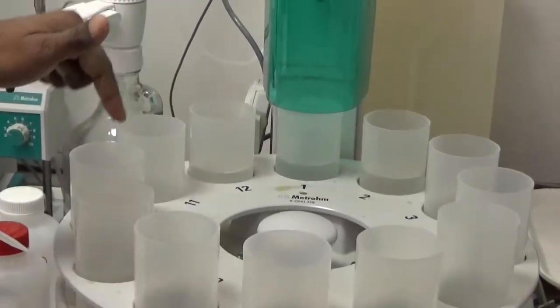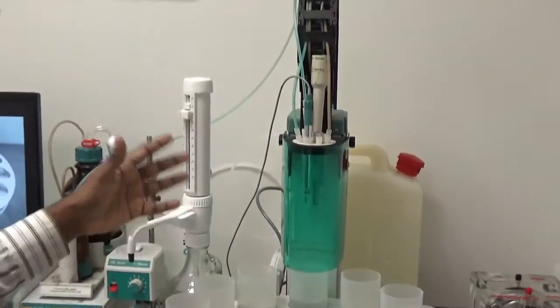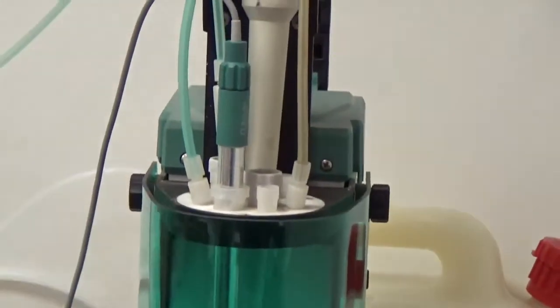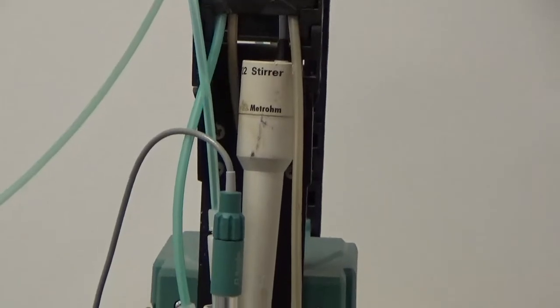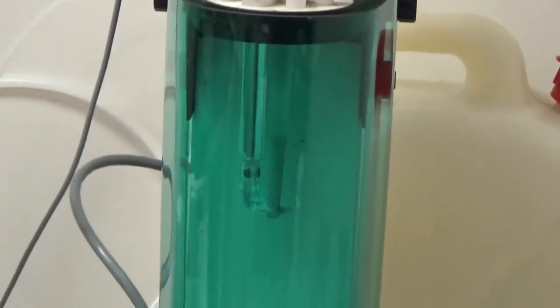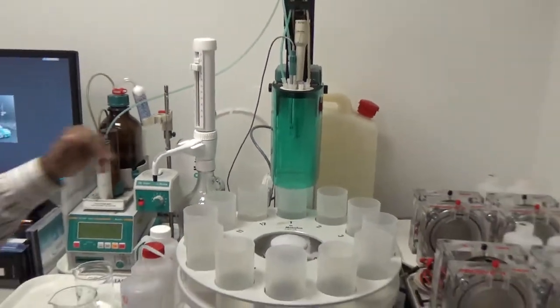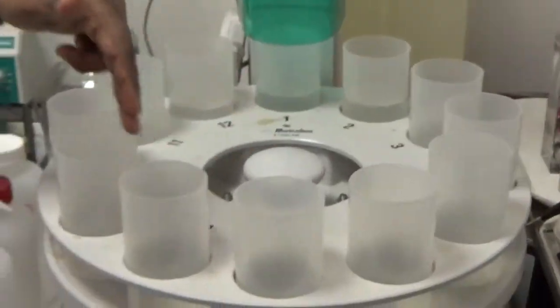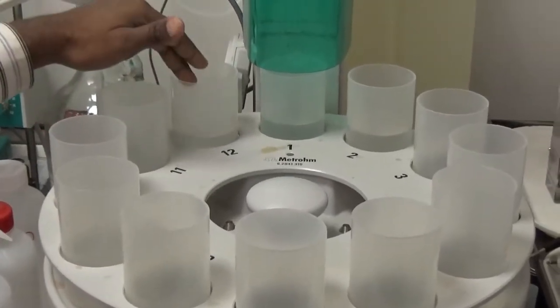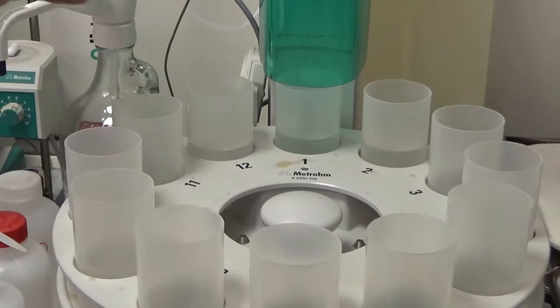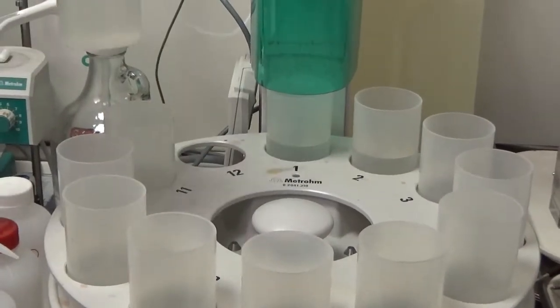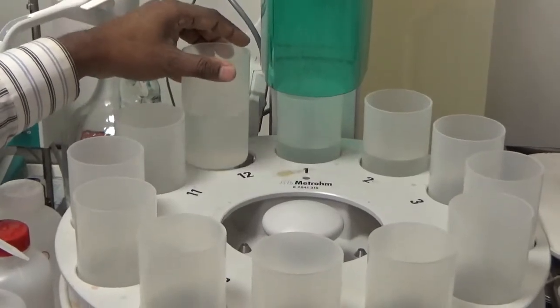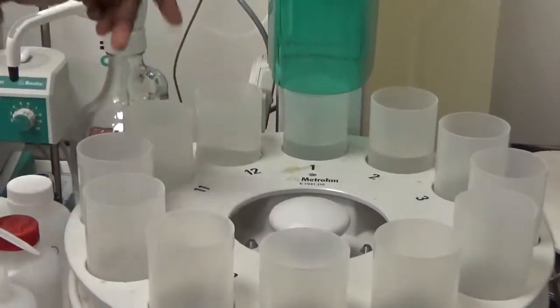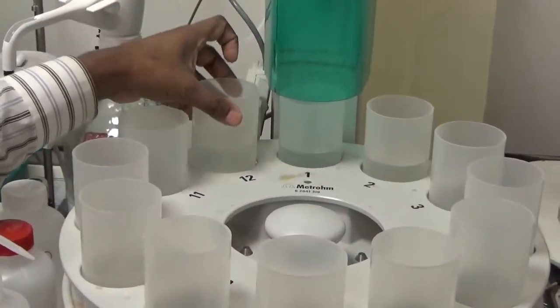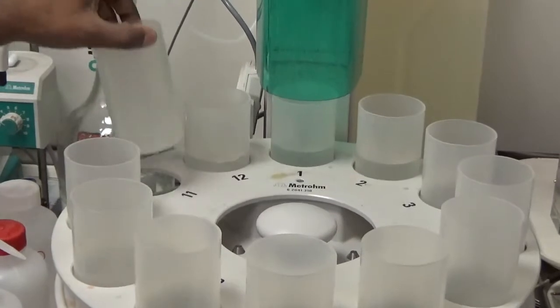We have 12 positions, and then we have the tower which moves the electrode and the burette up and down. When it is up, it's called home position. In the middle, it's lift position, and when it goes down to the beaker, it's the work position. Usually we put 10 samples from station number 1 up to station number 10, and then 11 and 12 we keep for rinsing and cleaning purposes. Sometimes we just use station number 12 with distilled water, which cleans the electrode and the burette. We can put 10 samples or 11 samples, depending on whether we use one position for cleaning or one position for cleaning and one for rinsing.